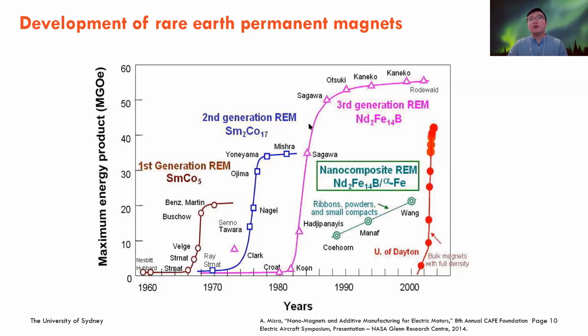Majorly the material was ferrite, but some brilliant researchers wondered whether they could use cobalt, iron, and also nickel, because they are all ferromagnetic elements, as a base, and whether they could add some rare earth elements, like samarium and also neodymium, to further enhance the magnetic properties. From them, they fabricated the samarium cobalt based first and second generations of rare earth permanent magnets. But the issue is still here. You can see the maximum energy product is only around 30 or 40 mega Gauss Oersted.